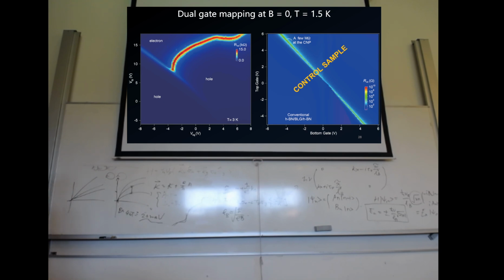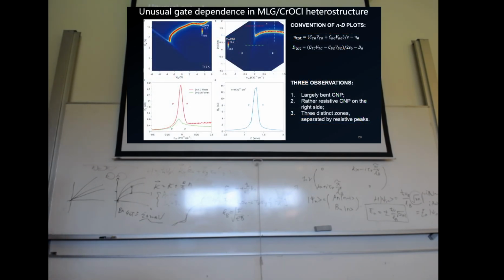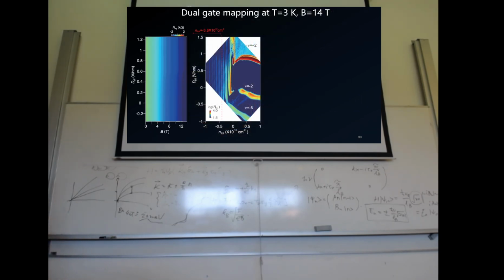Okay, and this is the sample with chromium oxychloride replaced. If we plot them from the dual gate mapping, where the color represents the resistance of the device, into displacement field and total carrier density using the formula we discussed a little bit yesterday, but not very precisely, now this is the precise formula. You can see that there is still the vertical line, but it stops there and then goes in another direction. The dashed line is the new charge neutrality point, and everywhere else is separated into the conduction band and valence band, corresponding to electrons and holes. Why so? The reason is that there's some kind of surface state. I will discuss that later.